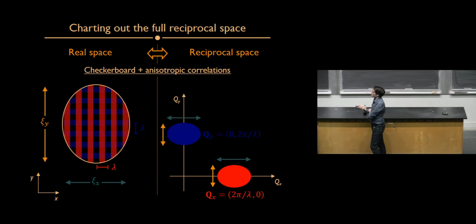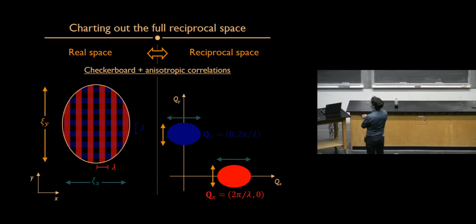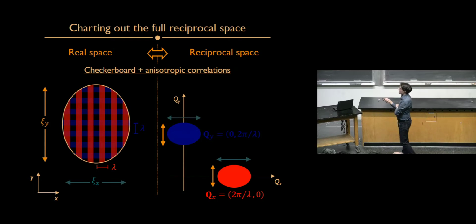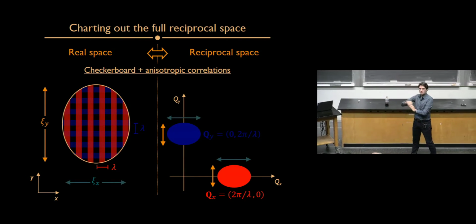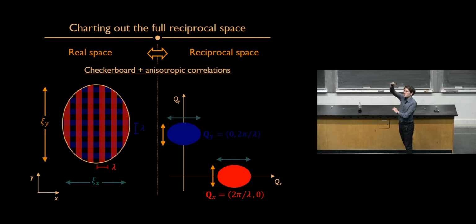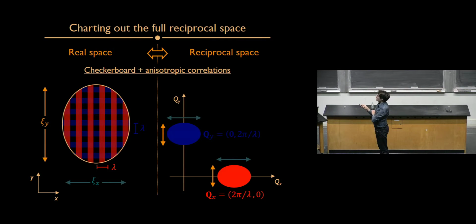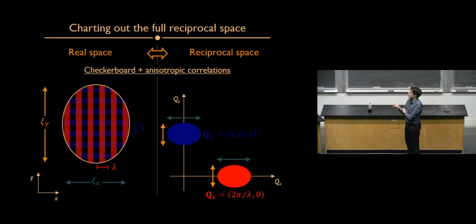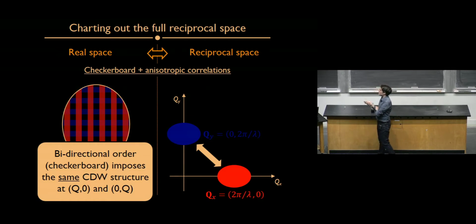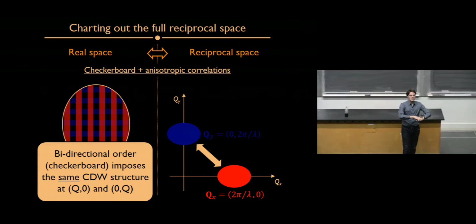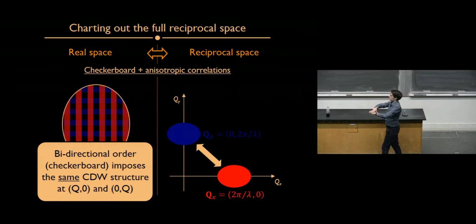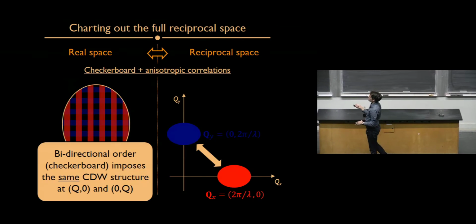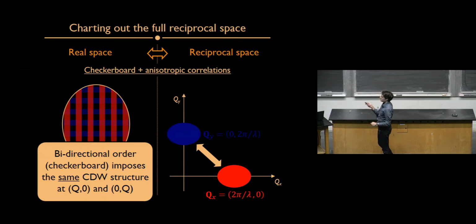So if I add another component now, which unfortunately you cannot see very well, and it doesn't come out very well on this projector, but I've just added another modulation in the vertical direction. So these are kind of horizontal stripes that are propagating along the vertical direction. Then that creates another peak here along the qy axis. And this peak has to have the same shape as this peak in reciprocal space, because they share the same domain structure here. They share the same correlation length. So the broadenings have to be the same. So if you have two orders present, two modulations along two directions present at the same time, then they should have the same structure in reciprocal space along one reciprocal axis and the other reciprocal axis.